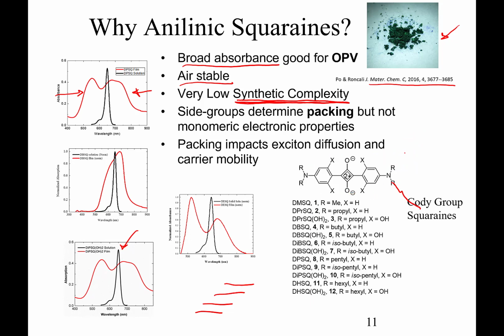So let's have a look at these side chains that we've made, that Dr. Cody's made, in a library of materials that we have on hand. It's these side groups that determine the packing, but not the electronic properties of the material in solution. If you look at all of these graphs, what we find is that the black curve in here always stays the same, independent of what the Squaraine is.